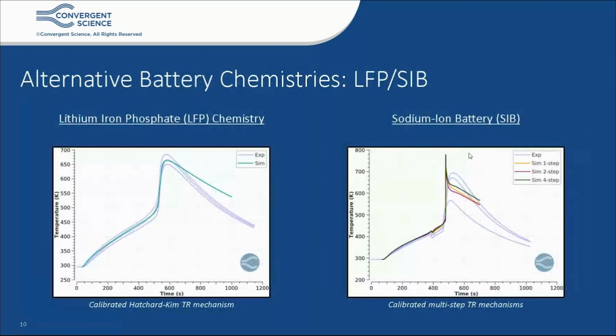We were also fortunate enough that IAV provided us experimental data for different battery chemistries, so we can check the robustness of our calibration approach, and robustness of different thermal runaway mechanisms available in literature. We received data for lithium iron phosphate, an LFP battery chemistry. In literature, we found researchers trying to employ the Hatchard-Kim four-step thermal runaway mechanism. So we calibrated the default Hatchard-Kim thermal runaway mechanism and optimized it to mimic the LFP data we received from IAV, and we match very well with the experimental data.